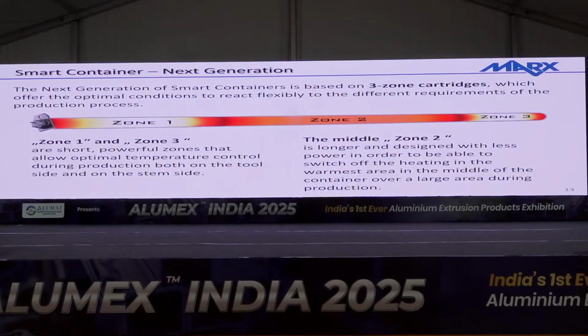They are very useful during the production. The middle zone, this is zone number 2. It's longer and designed with less power, so it can be shut off during the production. Because while producing, the billet has a high temperature, and this temperature is put into the container, and there is also a process temperature that is put into the container. So in this area we have a temperature belly, almost 50 degrees higher than the rest of the container. So we shut this zone off because we don't need the temperature in this zone anymore during production.